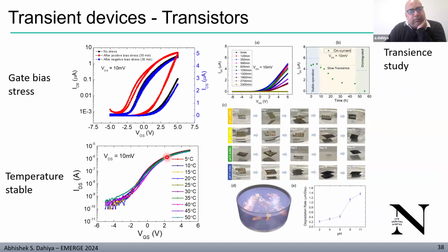Once we have done those stability tests, the continuous cycle test, we have also done some bias stress on these devices, applying both positive and negative bias stress, as well as at different temperatures. The scans show less influence of the temperature on the transfer characteristic. At the end, we see the slow transients of the devices. We put them in around the pH of the body fluid, 7.4 in this case, if I remember well, but we have also done it at different pH. For the degradation rate of the magnesium foil, as you can see in this graph, we have extracted the number, and these are the optical images of the devices under dissolution or degradation.